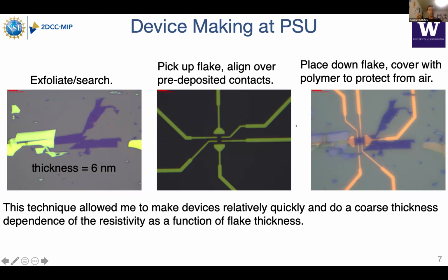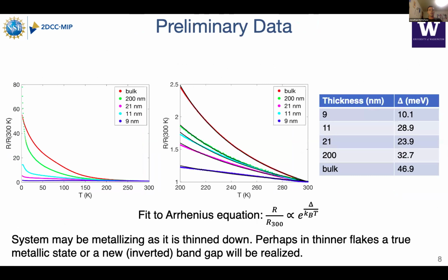And so this technique allowed me to make these very simple devices relatively quickly and do a coarse thickness dependence and see how the resistivity changes as a function of flake thickness. What I'm showing here on this slide is some preliminary data I took at Penn State. I have the normalized resistance, normalized such that it's 1 at room temperature, as a function of temperature for several different thicknesses. And we can see that broadly, as we thin this material down, it gets less and less resistive at low temperatures.